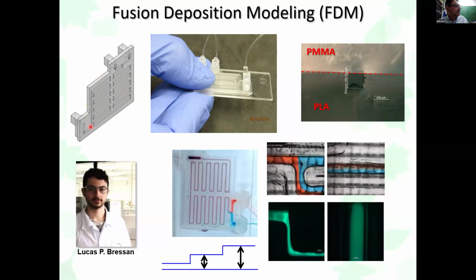And we used this strategy, this kind of design, to prepare a micromixer for different analytical applications. This is a micromixer. I think most people are familiar with mixers in microfluidics. But here we also have a feature that is a detection window in this position here. And using 3D printing, it is really easy to adjust the height of the detection window. So depending on the range of concentration you have, you can use a larger optical path, for example, for diluted solutions. If you have a concentrated solution, you can use a smaller optical path. So you can adjust it just for the concentrations of your application.